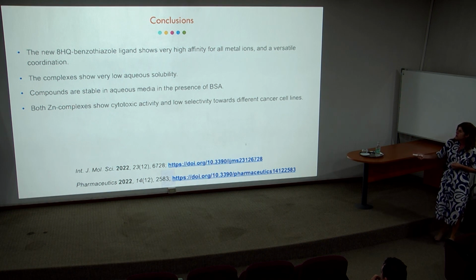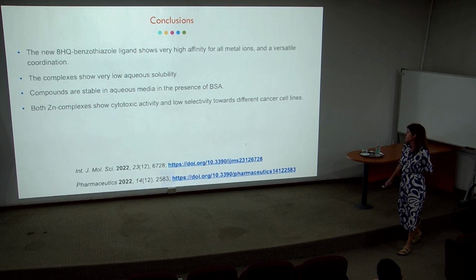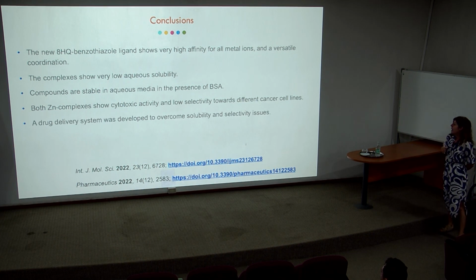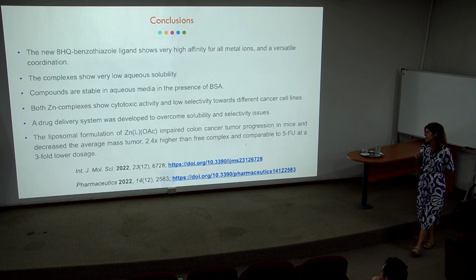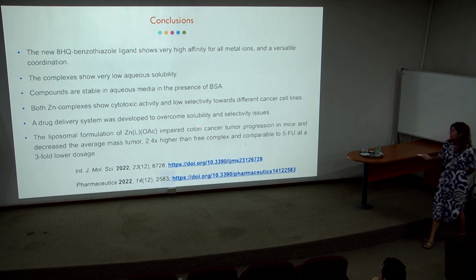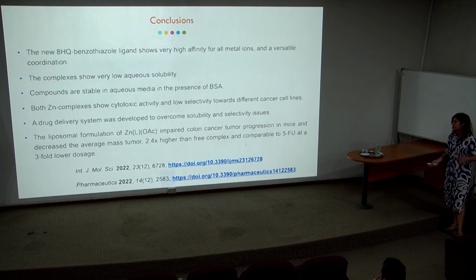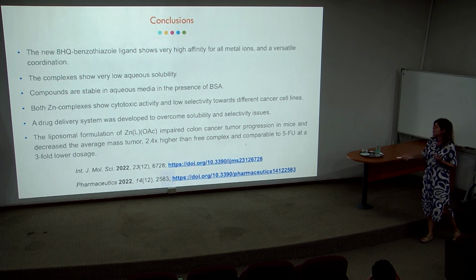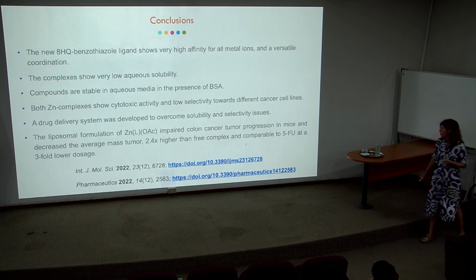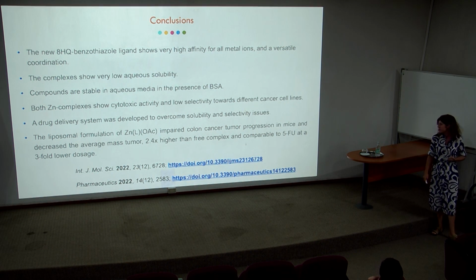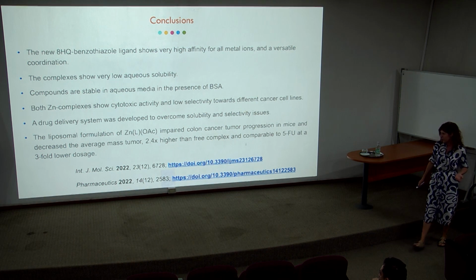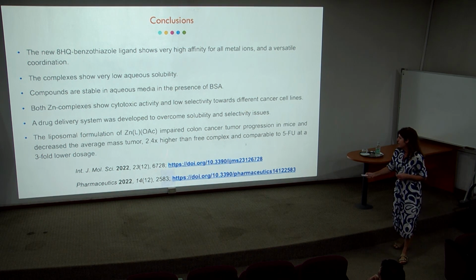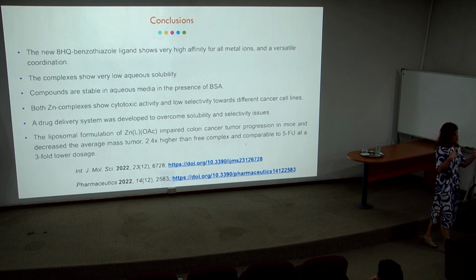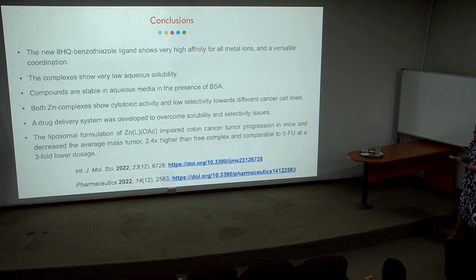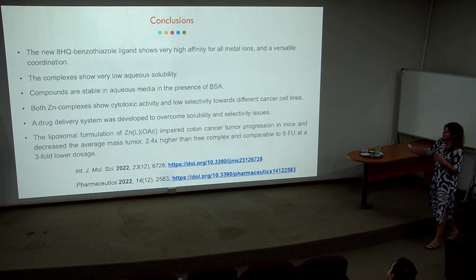Both zinc complexes show cytotoxic activity, but low selectivity towards different cancer cell lines. And the drug delivery system was developed to overcome solubility and selectivity issues. The liposomal formulation impaired colon cancer tumor progression in mice and decreased the average tumor mass 2.4 times more than the free complex, comparable to 5-fluorouracil at a 3-fold lower dosage. So this work has been published in 2 different papers, one dealing with zinc and the other dealing with the other metal complexes. And now I will switch to another system.